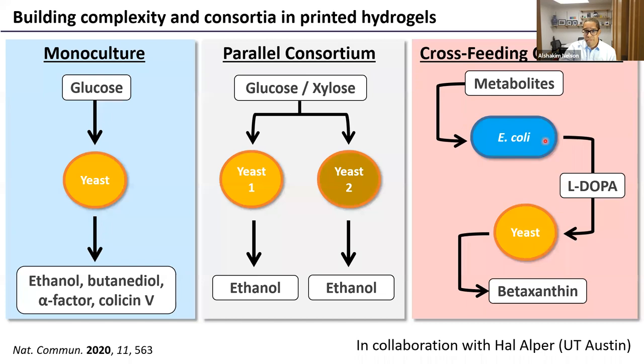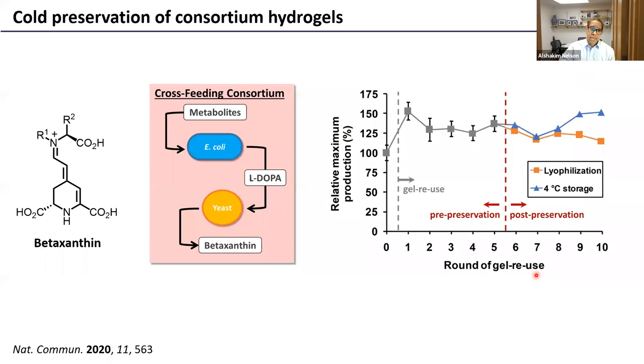And then finally, we've also produced this cross-feeding consortium where we can mix different families, where we have E. coli that's been engineered to produce L-DOPA, and then yeast that's been engineered to transform L-DOPA into betaxanthin. When we have this cross-feeding consortium, these are in two separate adjacent gels, I should mention. What we find is that, again, these structures are reusable over time, just like I showed with the first case, the production of ethanol from glucose. This is for the rounds of reuse across the x-axis here.